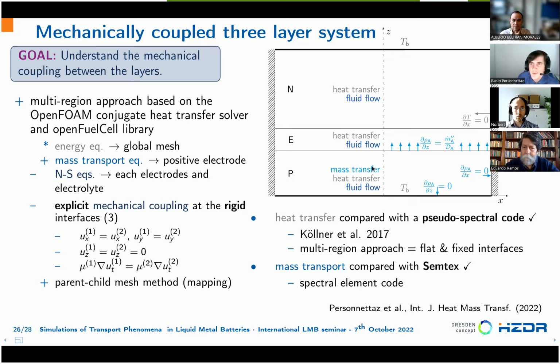The stable stratification in the positive electrode is very strong. So there is no chance, of course, we test only one material, and there are materials in which it may differ. In this case, we use lithium bismuth, and the two metals are very far away in the periodic table. They are very different in mass, and this means that mass transport is very important. If one considers, for example, two metals that are a bit closer in the periodic table, then we cannot rule out a priori the coupling between mass and heat transfer. But in the positive electrode, this is what one can usually assume.